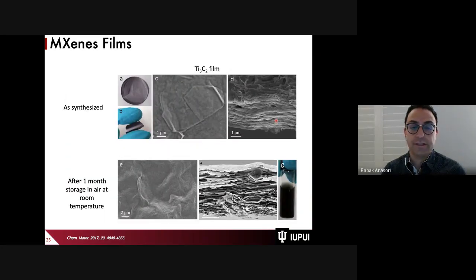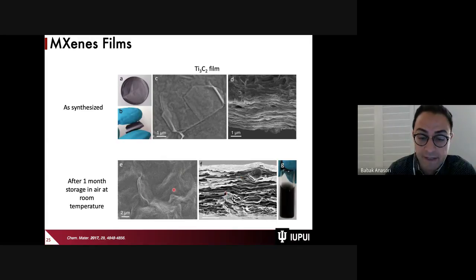Moving forward, we have these MXene films that we can synthesize, and as I said, they are single atomic or few atom layers, 1 nanometer thick. Obviously, like any transition metal carbide, they are expected to get oxidized, and they will get oxidized. But if we stack many of them over each other, then the chances of oxidation reduce significantly, and they can live a lot longer in the environment.